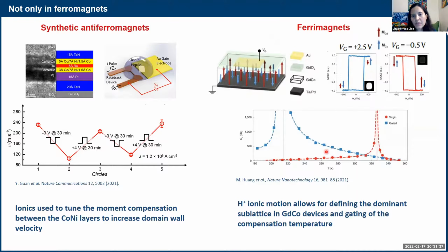And in these systems, if you do a study of the coercivity as a function of temperature, you typically find in ferrimagnets this compensation temperature. At some point, the two lattices are perfectly compensated, and at that point, the coercivity diverges. And they could see that they could move this around with a gate. So that's also a really nice functionality in ferrimagnets.